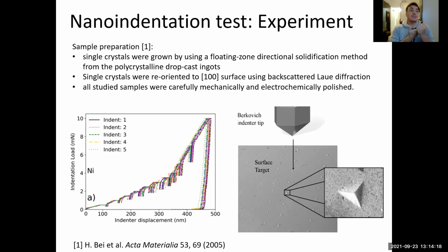And with this so-called load displacement curve, one can even track the experiment, how you are doing the loading process of the Berkovich tip. This is a Berkovich tip. In the experiments, they use a diamond Berkovich indenter tip to perform the nanoindentation test. They are loading, and then they are unloading. This is an SEM image of the target surface. This is nickel, and they can perfectly visualize the mark of the indenter on the surface. Then you can see here the loading process, the maximum indentation depth that they reach, and then the unloading process. And here is the recovery of the material. I'm going to explain a little bit more how to read this kind of graph for the MD simulations.